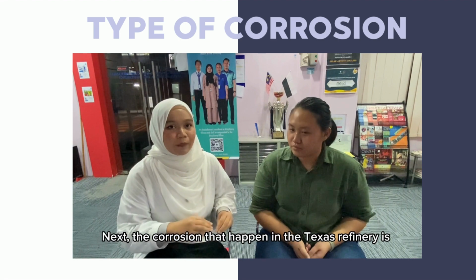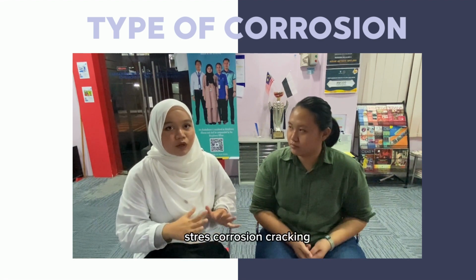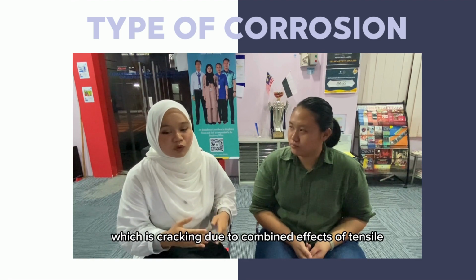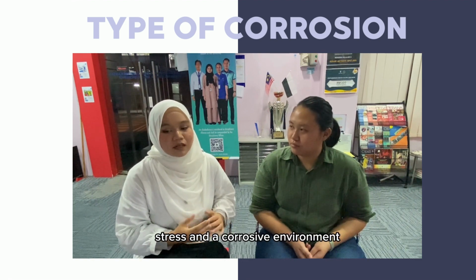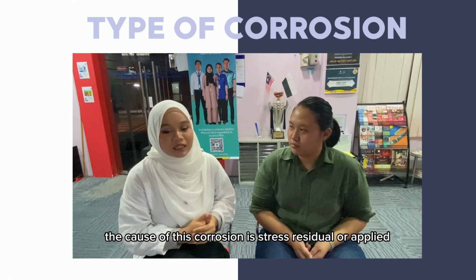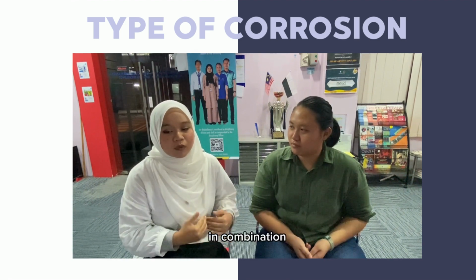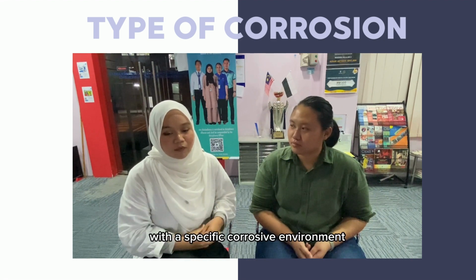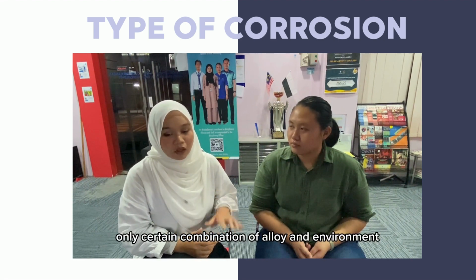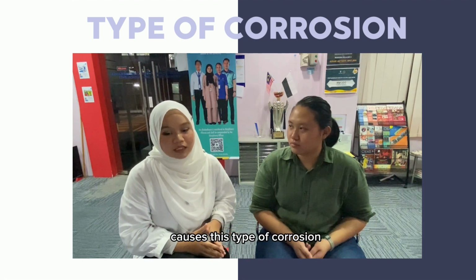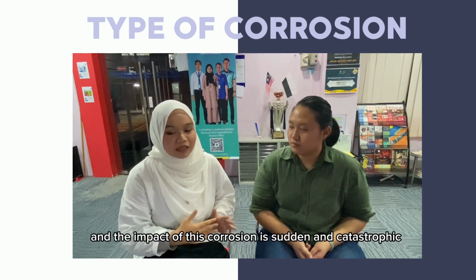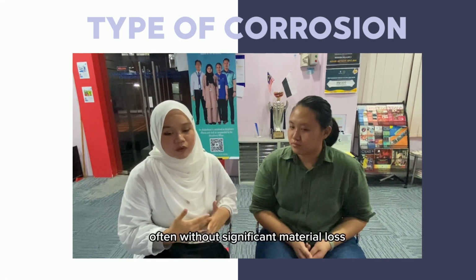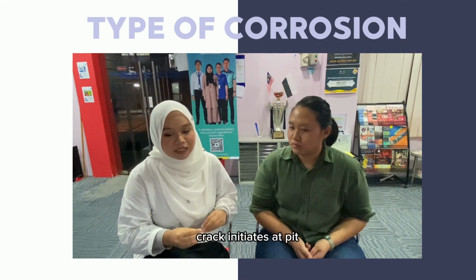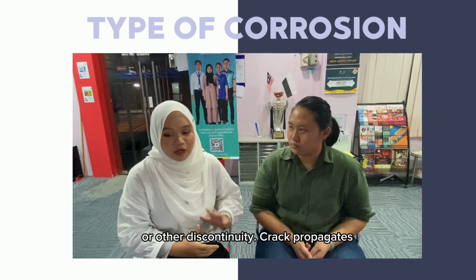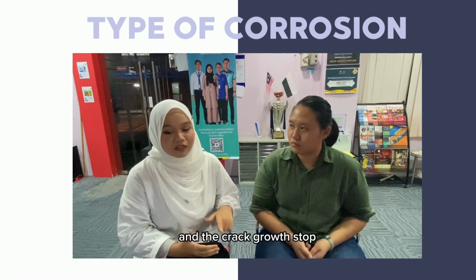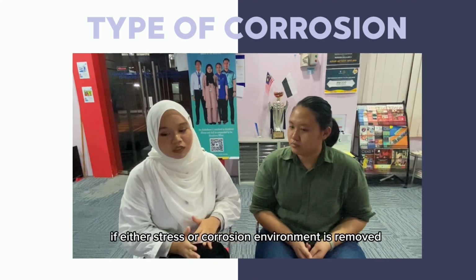Next, the corrosion that happened in the Texas refinery is stress corrosion cracking, which is cracking due to the combined effects of tensile stress and a corrosive environment. The cause is stress, residual or applied, in combination with a specific corrosive environment. Only certain combinations of alloy and environment cause this type of corrosion. The impact is sudden and catastrophic failure, often without significant material loss. Cracks initiate at pits or other discontinuities and propagate perpendicular to the stress, and crack growth stops if either the stress or the corrosive environment is removed.